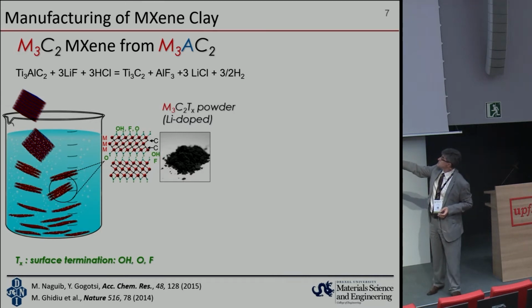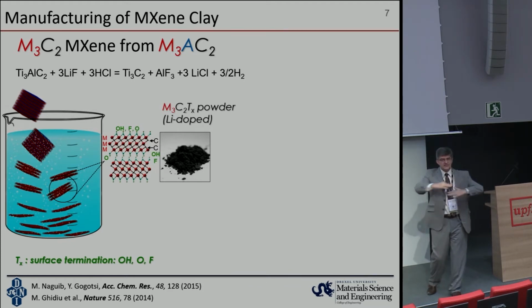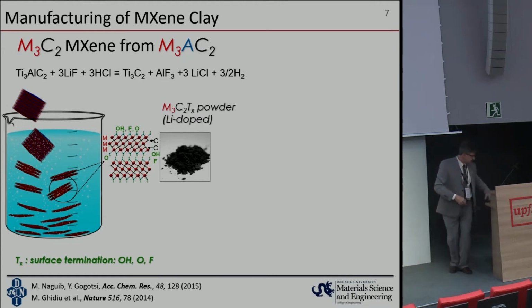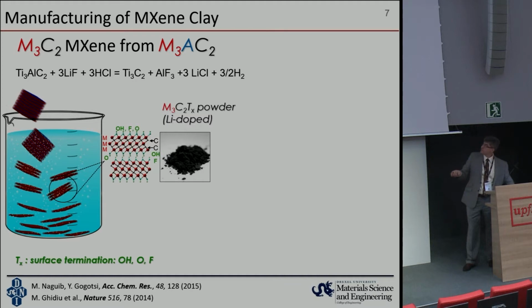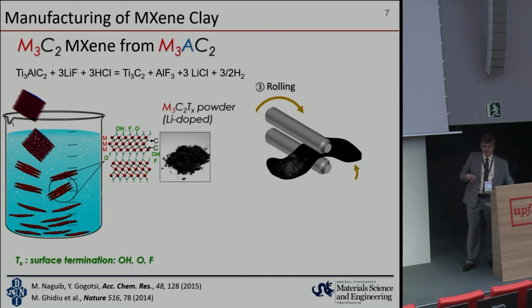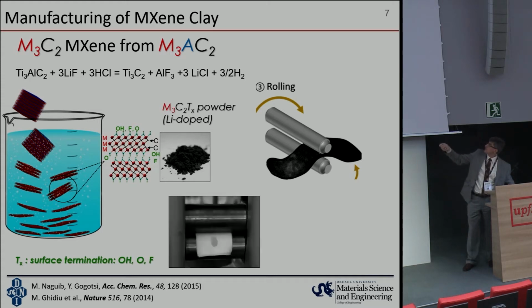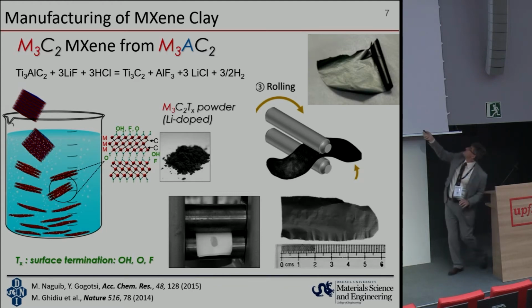Moreover, what is interesting happening? Lithium ions will go with water and intercalate between the layers of MXene sheets, giving it rheological properties of clay. So what we can do, we can etch powder, and after that take a wet slurry or dry it and add a couple of drops of water, and we get a material which we can roll right away. For example, this type of a foil.